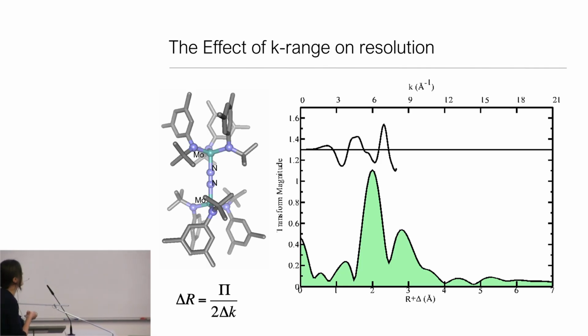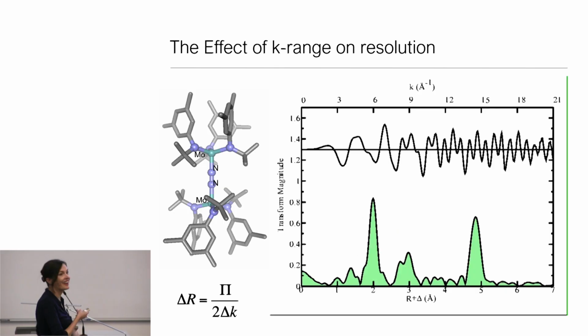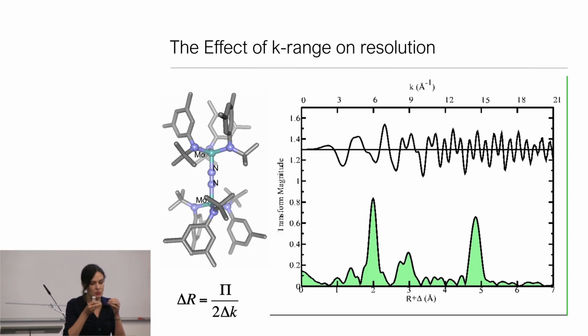But I just want to give you a sense of what it looks like to have very high K data. So I've taken this beautiful data. This is a sample made in Kit Cummins' lab at MIT, and the data were collected by Graham George at SSRL. These are record high K data going out to K of 21, largely because you have this linear molybdenum, nitrogen, nitrogen, molybdenum vector that gives you a beautiful forward scattering effect. When I look at how this modulates the EXAFS, you can see as I go further and further out in K, I start to sharpen up the Fourier transform and I start to see features that weren't there. We'll go back one more time, it was fast. I need to slow it down, but you can see how the structure emerges. This is why an XAS spectroscopist spends so much time trying to get data to emerge from the noise, because that's where their resolution is actually going to come from.